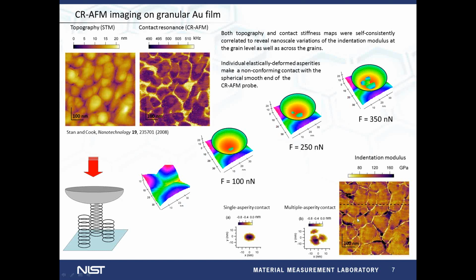the elastic modulus. So what we see here in the elastic modulus map is a consistent decrease, about 20% of the elastic modulus in the intergrain regions compared with the grain regions, associated with intergrain softening due to the orientation mismatch between adjacent grains. And it's interesting because if we look at the contact resonance map, we have higher values for the resonance frequency in intergrain regions, which means higher contact stiffnesses, but not necessarily higher modulus.